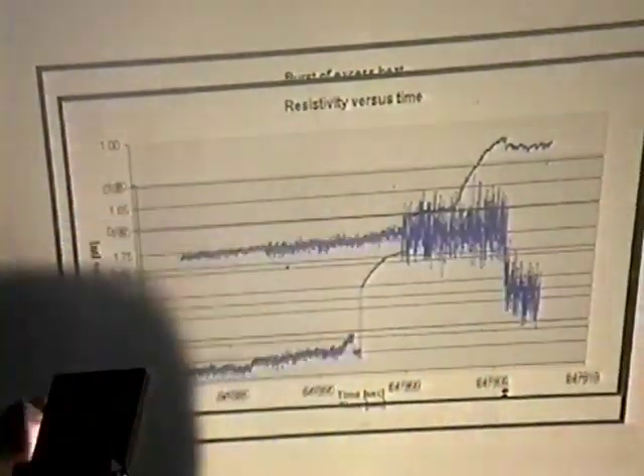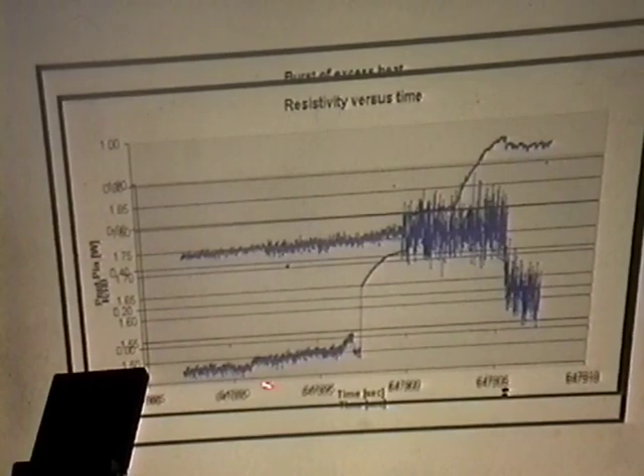You can see that at this particular time, we'd gone over the top of the loading curve and we're coming back down in resistivity, but it started going up again slightly, and then we hit what we'll, for lack of better terminology, call a resistivity oscillation. You can see this occurred very distinctly over 5 seconds, and then this rapid drop. Concurrently with that, the heat release, which I'll try to superimpose, which is this line here and goes up,